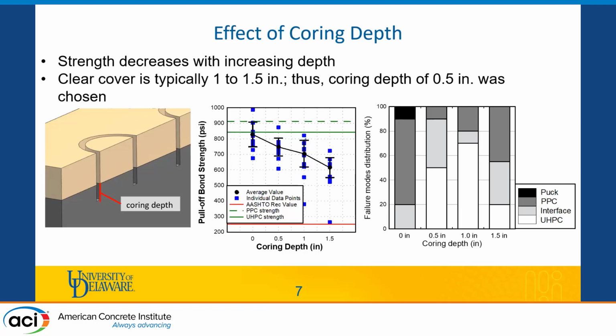And we can also see that all the results are above the AASHTO requirement, which is a good sign. Since we needed to decide which coring depth to adopt here, we wanted the coring depth that shows more failures at the interface, because that's what we are testing. The failure mode distribution shows here that the 0.5 inches has more failure modes at the interface. There is another point here, which is that the clear cover in the field is approximately 1 to 1.5 inches, and we didn't want to run into the reinforcement when we are conducting our test in the field. So we finally chose 0.5 inches of coring depth.